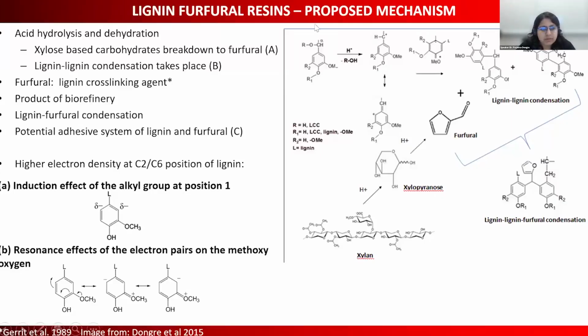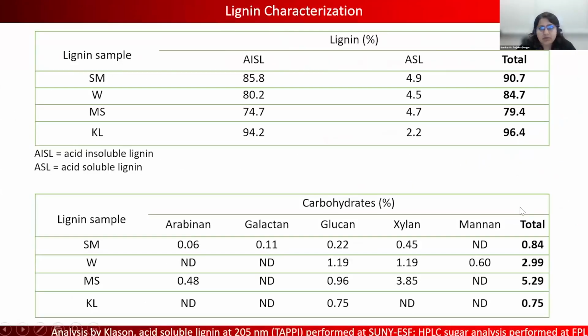And therefore, creating the adhesive system of lignin and furfural, as you can see from this diagram. So we were expecting that there would be in situ furfural present in the lignin that would act as the cross-linker. However, before I go into the synthesis method, this is the lignin characterization of the different lignins that were produced from the hot water extraction process.